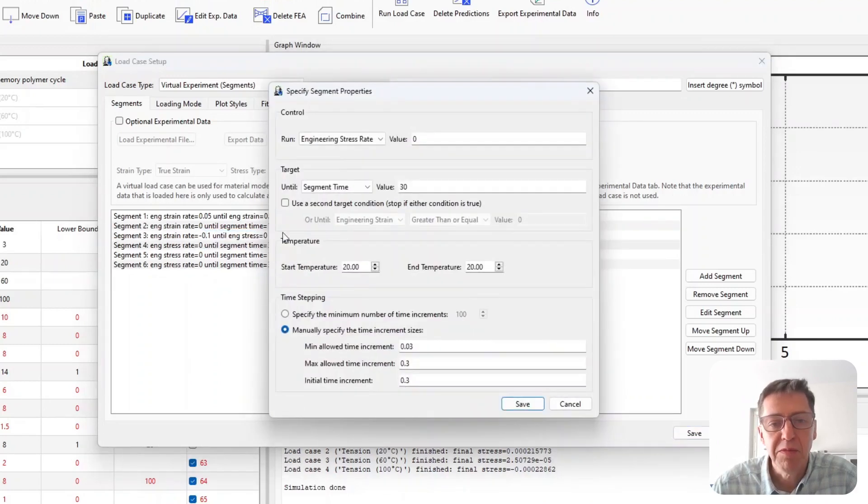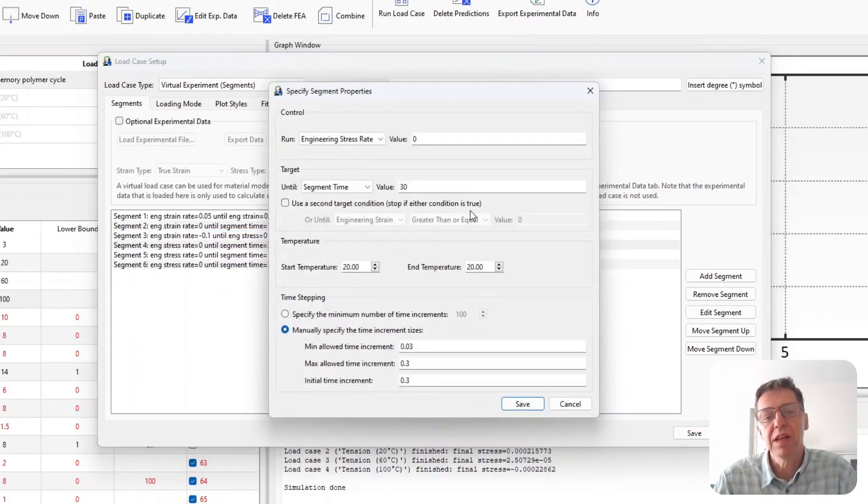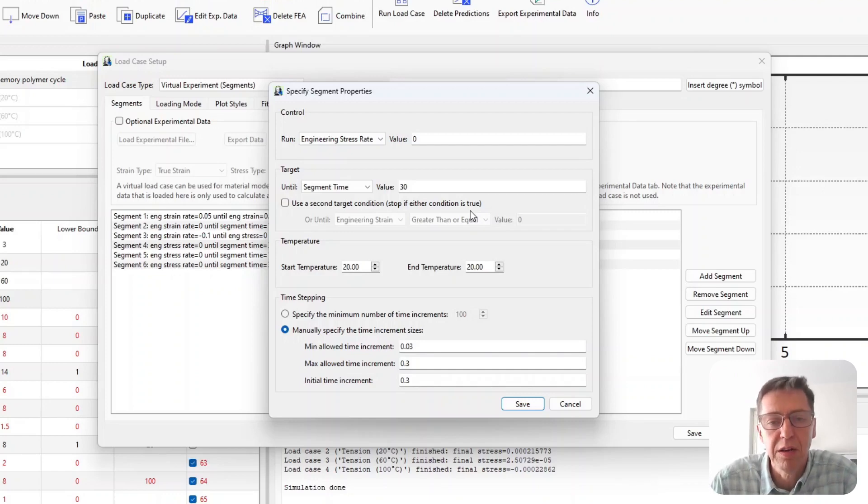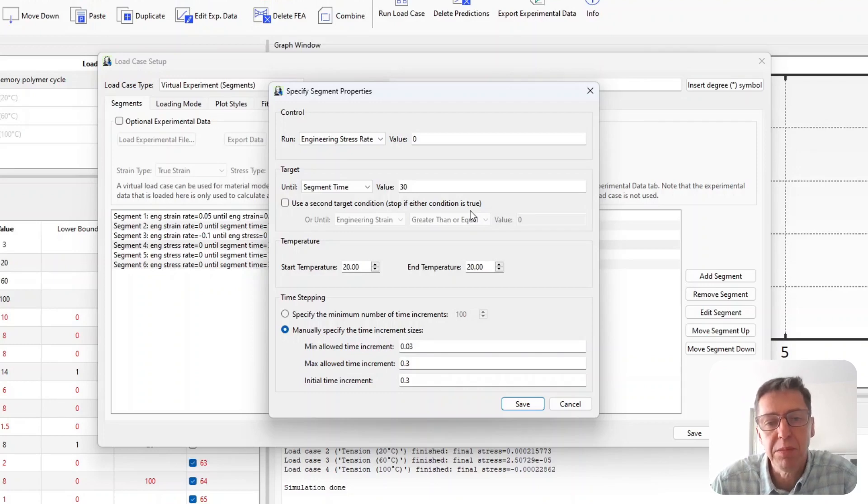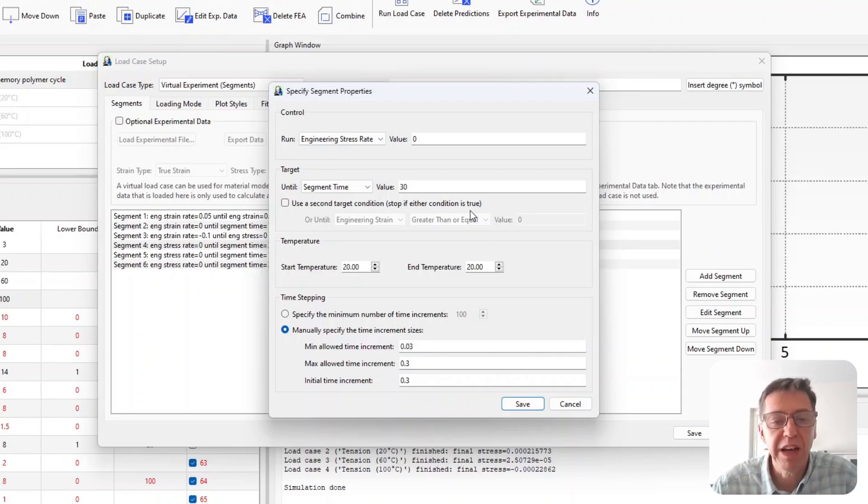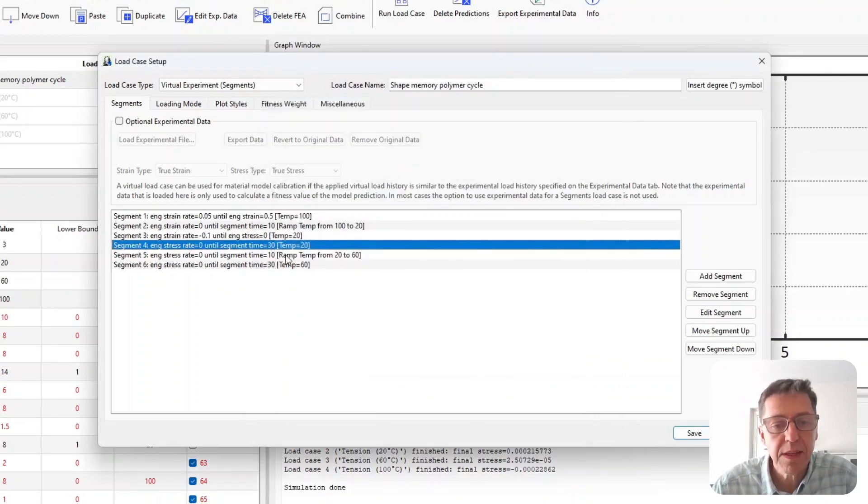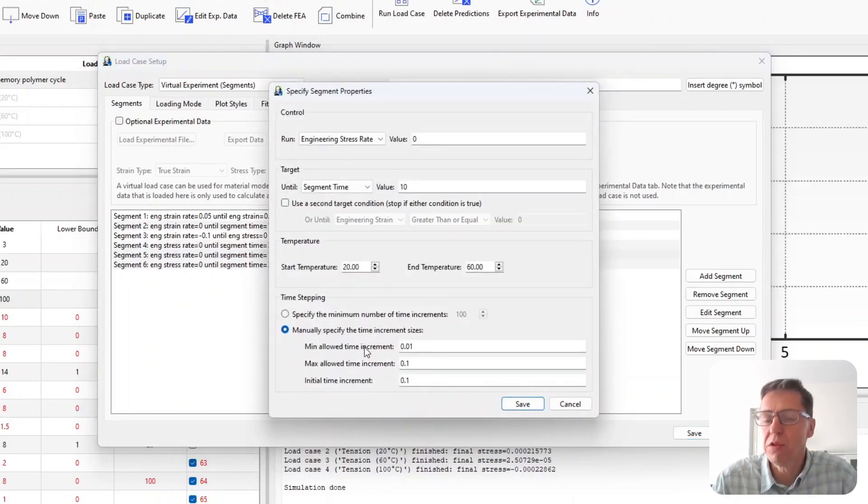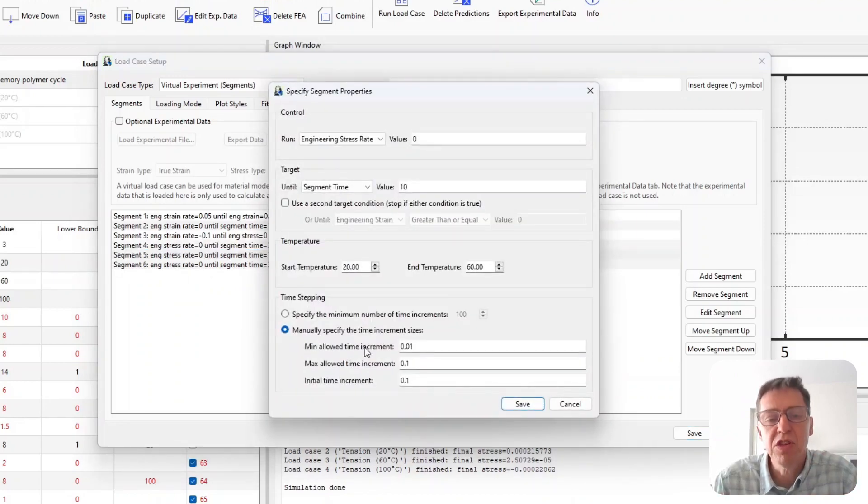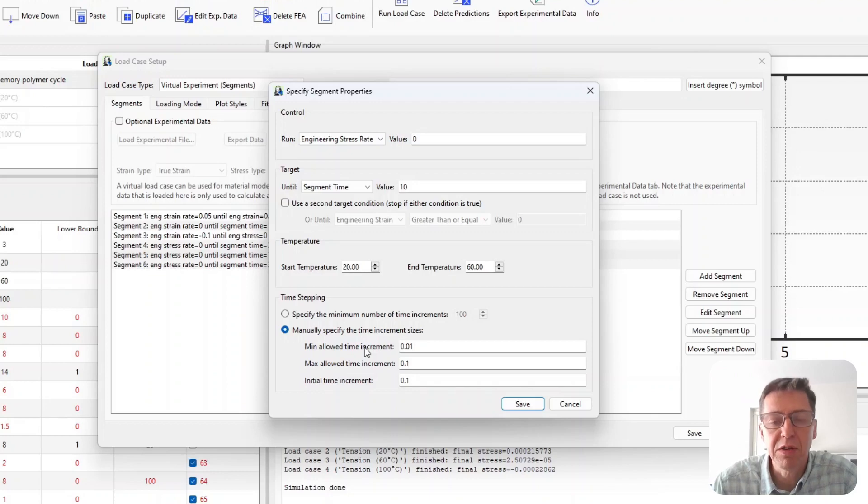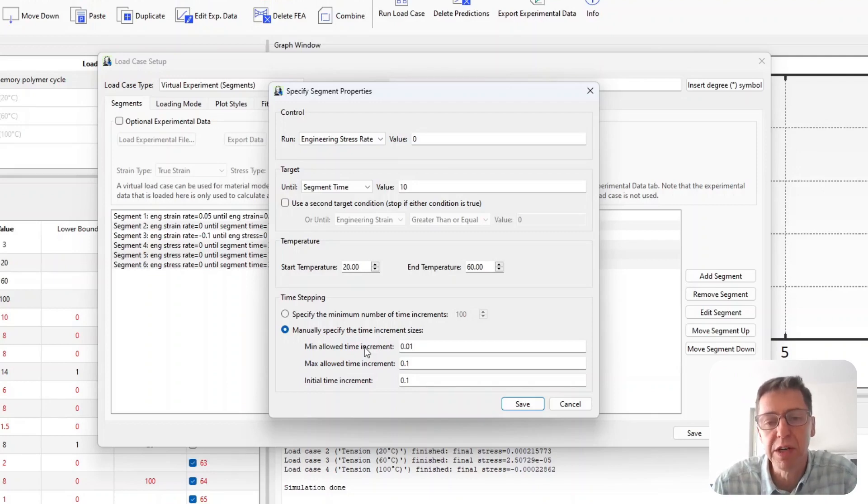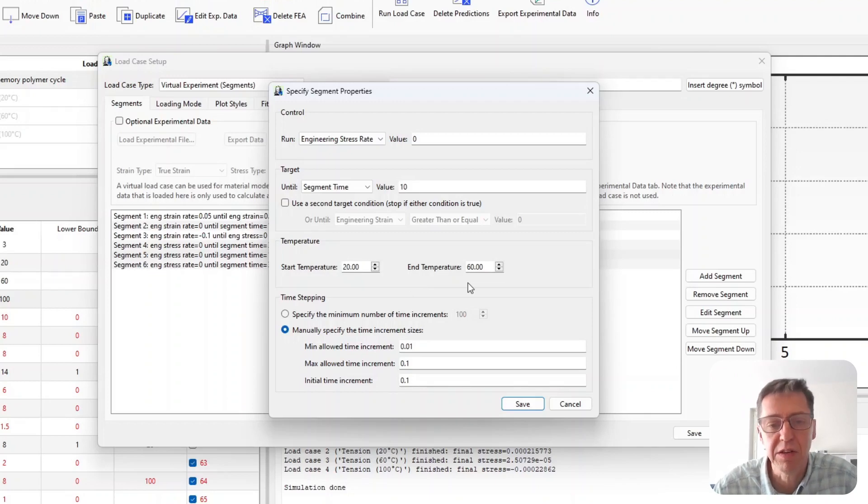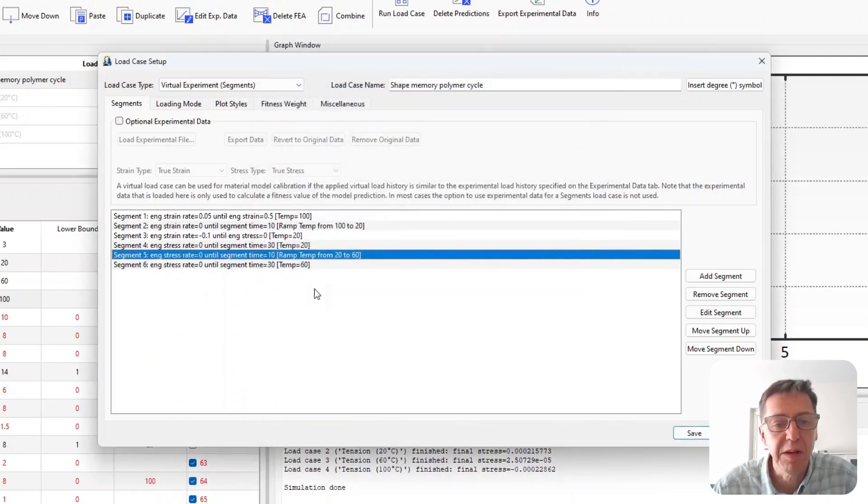Step four is that I'm just holding it constant at zero, at room temperature. Let it sit on the table basically, no deformation applied, no stress applied, and we let the material relax if it wants to. And then I do this temperature ramp, the external environment change that I'm interested in. Will this material recover now when we increase the temperature from 20 to 60°C, so the intermediate temperature of interest.